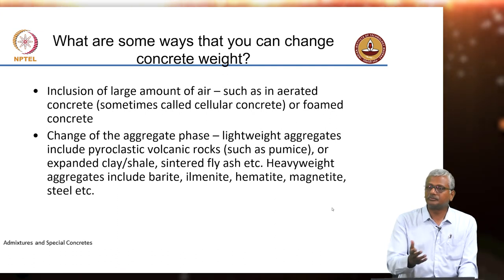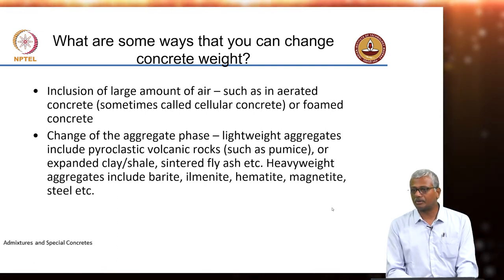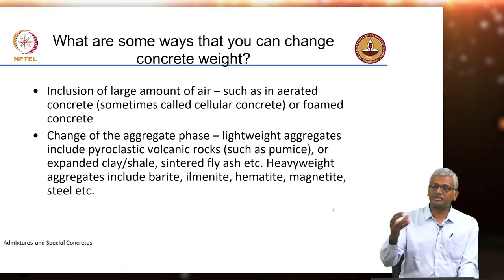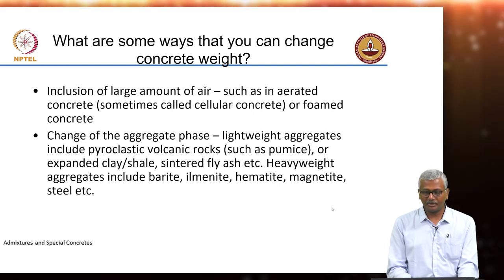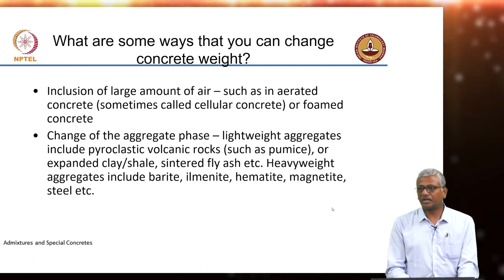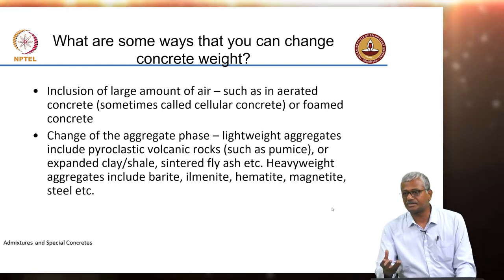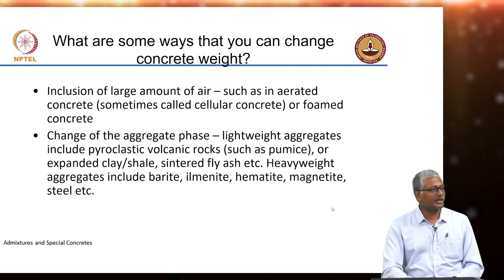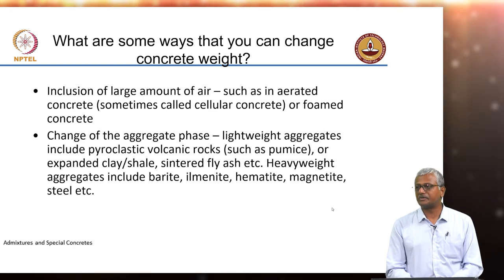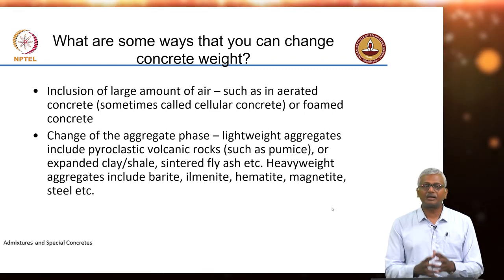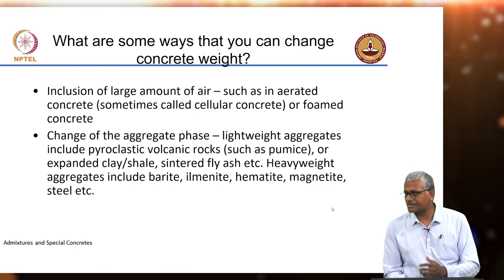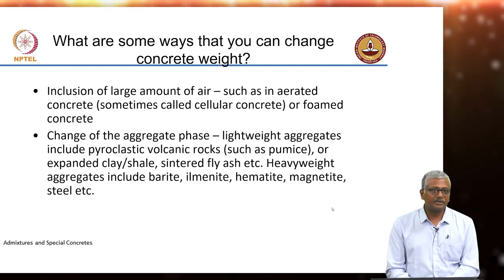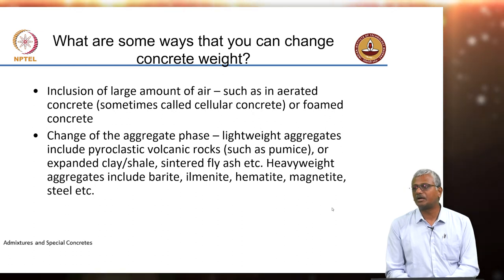Lightweight means density less than 1800, so you introduce much more air compared to air entrained concrete. Commonly today we use products like aerated concrete, also called cellular concrete, where large air pockets are put inside the system. We can also use foaming agents — similar to shampoo foam — mixed with cement paste or mortar, and the air structure is maintained once hardening occurs. For heavyweight concrete, however, the only option is to change the aggregate phase; you cannot make cement paste heavyweight.